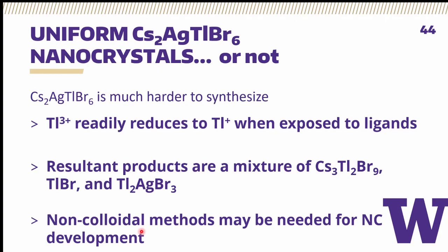Unfortunately, I don't have good news about the final step that we were hoping to achieve. After many, many, many attempts, it appears that we can't use current nanocrystal synthesis methods to get cesium silver thallium bromide nanocrystals. We find that thallium 3+ reduces almost immediately to thallium 1+ when exposed to the amine ligand, which is very important for getting nanocrystals out of your reaction mixture.